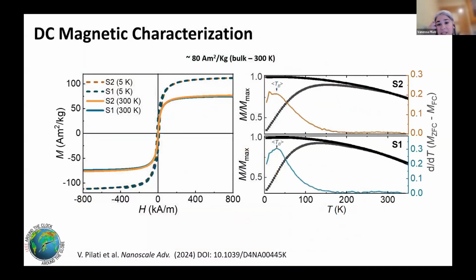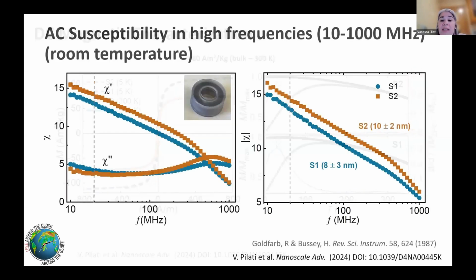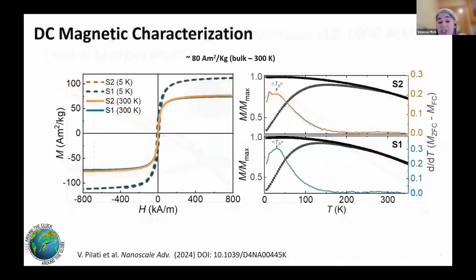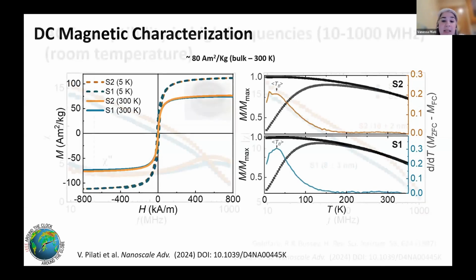From the magnetic characterization, we can see that at low temperature, they have a very, very small magnetic anisotropy, a very small coercivity, which is related to the small magnetic anisotropy. We can see that at room temperature, they are all superparamagnetic, the entire size distribution. We confirm this by the ZFC-FC curves and this distribution of blocking temperatures. And also we saw that the saturation magnetization that we can achieve is very close to the bulk manganese ferrite.